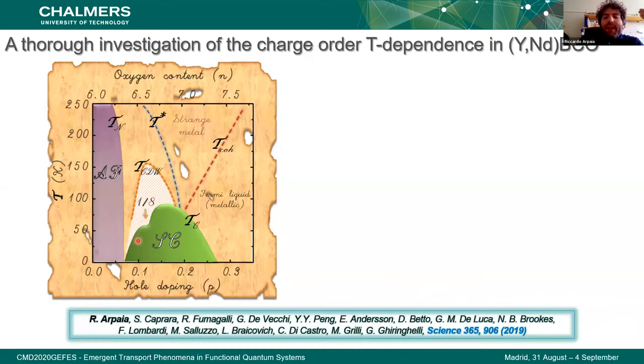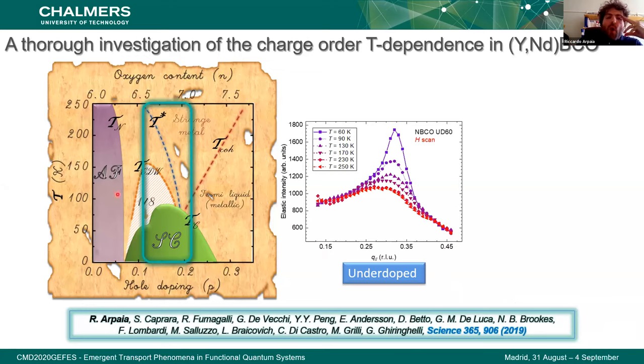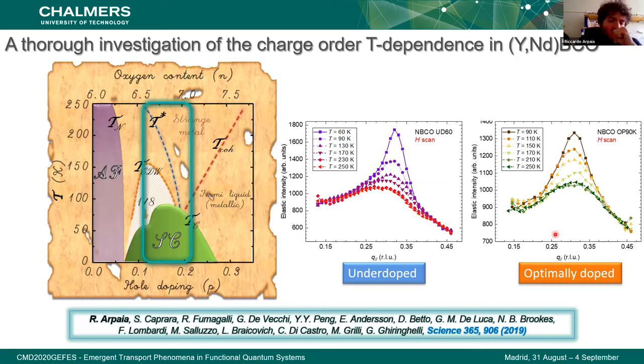So what we have done is just to repeat the experiment from 2010 again on the same sample, on YBCO, in a very wide range of doping and in temperature, and by using this new system. And what we've seen is that basically we have a strong charge density wave peak at low temperature that becomes smaller and smaller when you're increasing the temperature, but still we see a clear broad peak, which is an indication of a quite short range charge density signal, even at very high temperature, even above the pseudogap temperature. And this has been seen both at the underdoped level and at the optimally doped level.